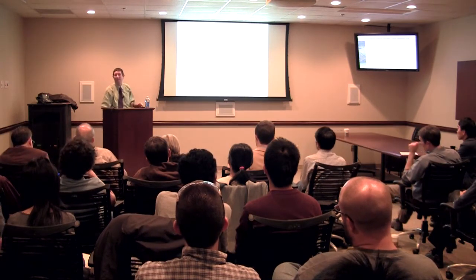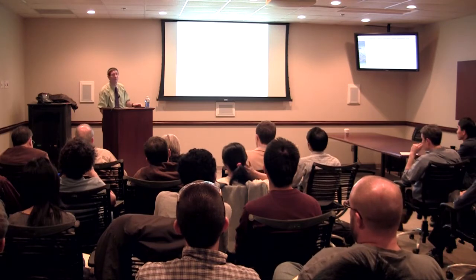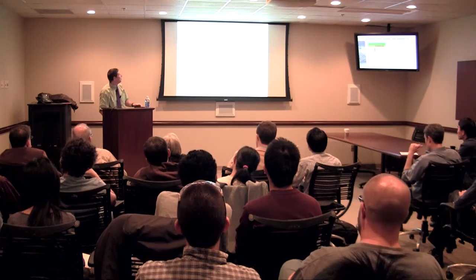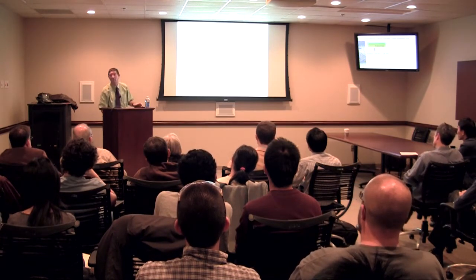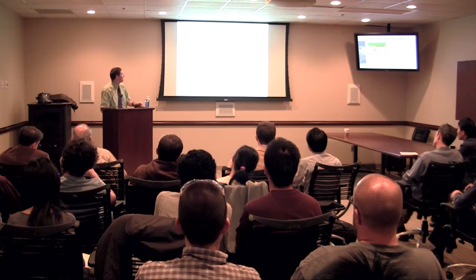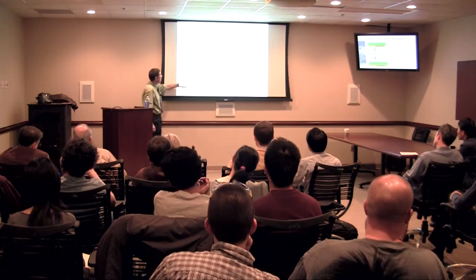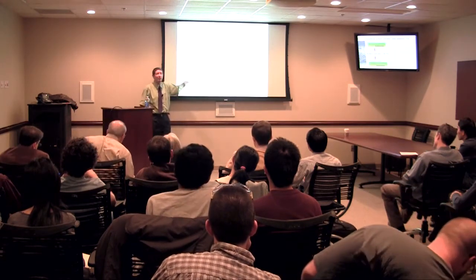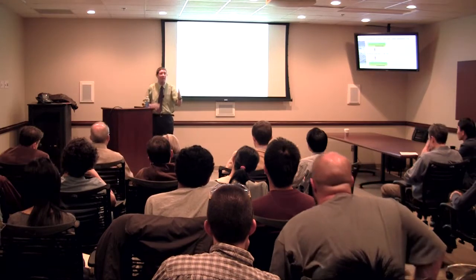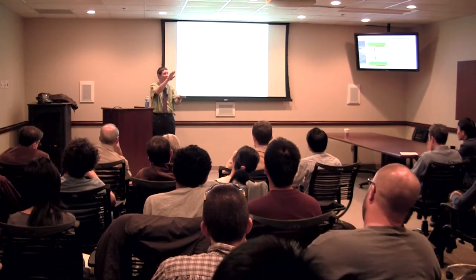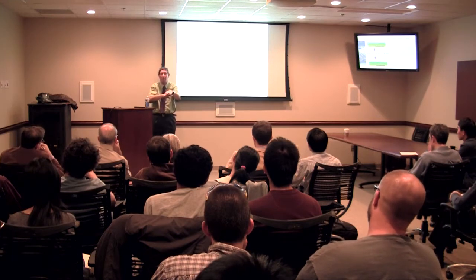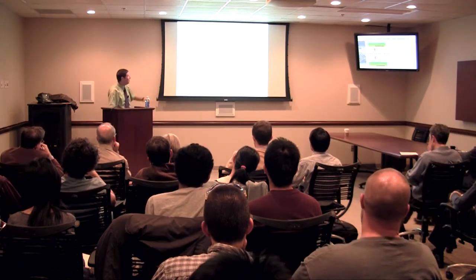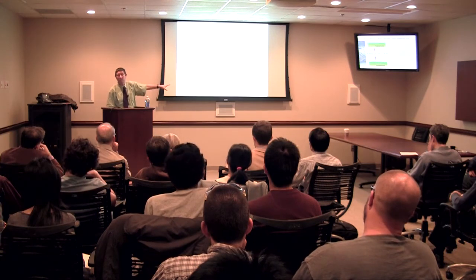Now, in the good old days, and this is also one of the old IBM patents from many years ago, I think it was dated in the 50s or the 60s, what they did, they took the substrate, the insulator, and dipped it in a solution with palladium, typically palladium chloride or some palladium complex. And what happens, you have nanodots of palladium on top of it, and these nanodots catalyze the two parallel reactions, the reaction of depositing the metal and the oxidation of the reducing agent. This works fine. This is the way people use to deposit on PC boards.